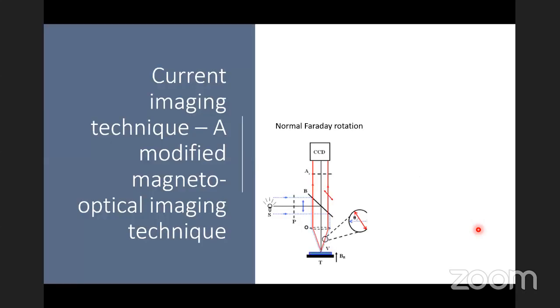The technique that we use is a modified version of the magneto-optical imaging technique, which we have been working on for a very long time and improving in various ways. Basically, the technique is normal Faraday rotation, but with very high sensitivity. You come in with linearly polarized light, which reflects from the surface of a sample, and the polarized light undergoes a Faraday rotation. The angle by which it rotates is proportional to the local field present on the material. And we image the intensity of the Faraday rotated light.